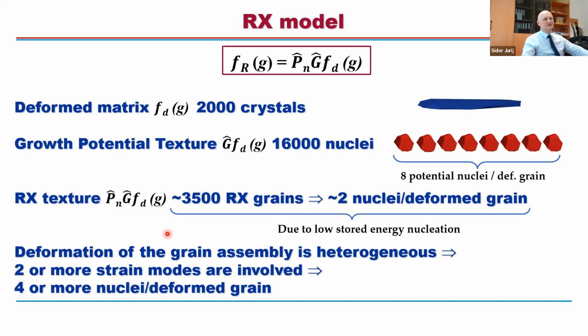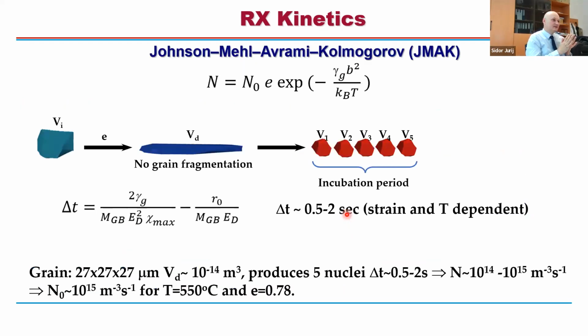However, the deformation of the grain assembly is heterogeneous, so you have not only one strain mode internally, you have always more, especially if you have particle effect deformation. So then you have at least another 3 strain modes. If you have deformation bands or shear bands or whatever, then even the most homogeneous macroscopic strain mode will internally be accommodated completely differently. So instead of one strain mode, you will have more. So sometimes you might have 4 or more nuclei, so you have to double or even triple the amount of nuclei due to these different strain modes. Okay, so on average, I say that one grain might produce approximately 5 nuclei.